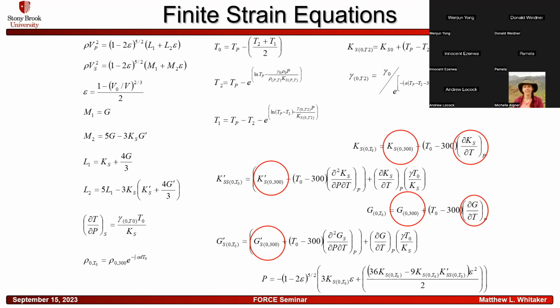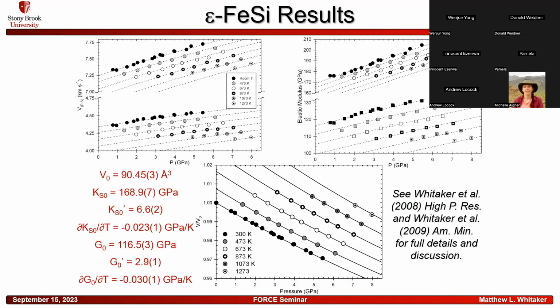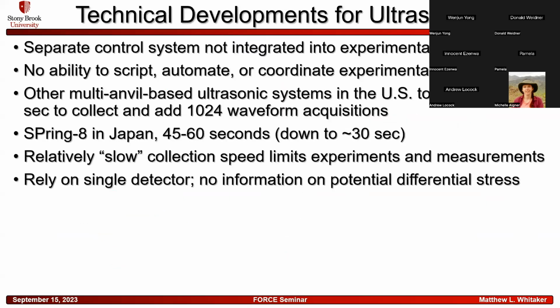Once we have this information combined with all of the data that we collected, we can then model a material's behavior under any set of pressure and temperature conditions that we need. This is just an example of that on epsilon iron silicide, where we have the P and S wave velocities at the top left shown as a function of pressure, and the elastic moduli on the top right. We were able to fit these data and determine the elastic properties of this material for the first time using this type of ultrasonic experiment at high pressure. And this is what I did for my dissertation at Stony Brook.